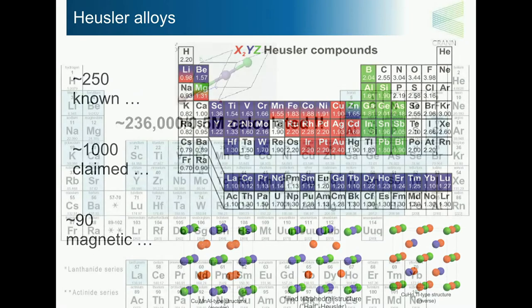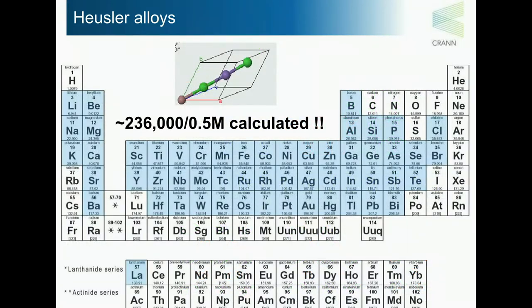So what we did was we constructed all the Heusler you can make out of all the elements you see in blue. And if you run the combinatorial analysis, you find out that you have about a quarter of a million prototypes. If you want to play a little bit with magnetic order and so on, it turns out that we did about half a million calculations. So this is a simple calculation, a unit cell type of calculation, but you have to do half a million of them.